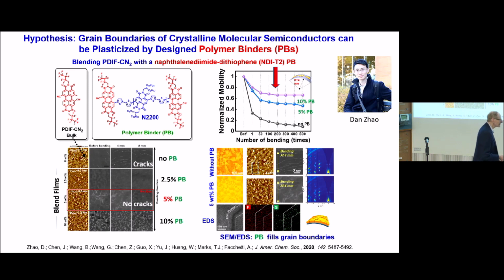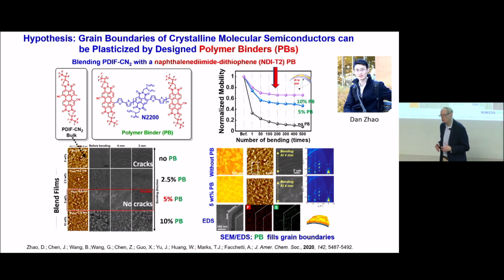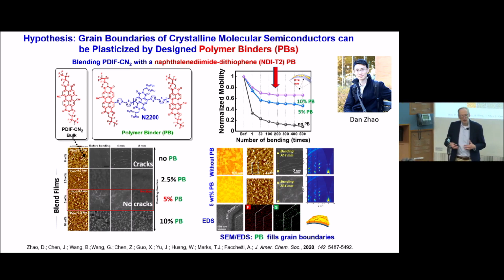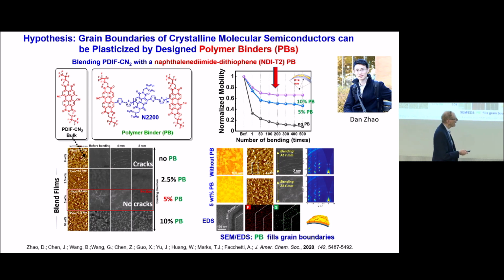So you might say, yeah, but how the heck do you know that that's really what you've done? So we do a lot of microscopy, where we see as we add more and more of the polymer binder to plasticize the grain boundaries, you don't see cracking anymore. But also we can do EDS, scanning electron microscopy, and you can see this guy has sulfur, these have fluorine. So with the EDS you can do a spatial mapping of the elements present. And you can see that it's behaving just like we predicted.